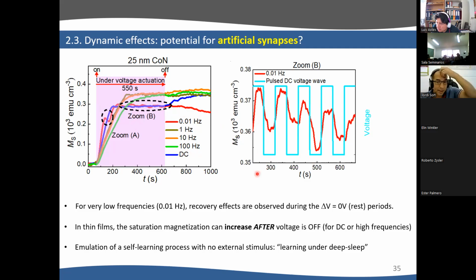But there is even another interesting observation, and this is the comparison between the blue and the red curve. The blue here is a 25 nanometers DC, the voltage is applied DC for 600 seconds. And what you can see here is that when we stop the voltage, there is no relaxation, but the magnetization continues to increase. And this is a very fancy effect that cannot be mimicked with other types of neuromorphic materials like resistive switching or spintronic materials. It's hard to obtain this behavior.